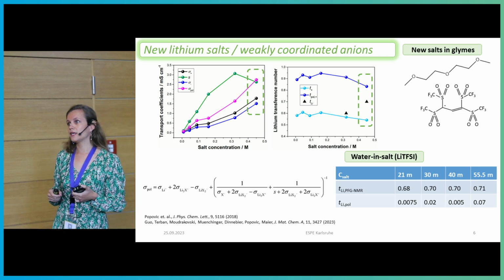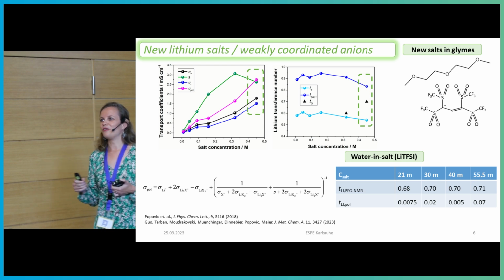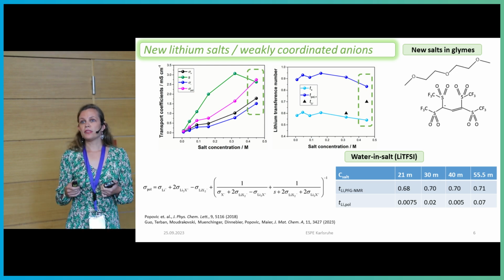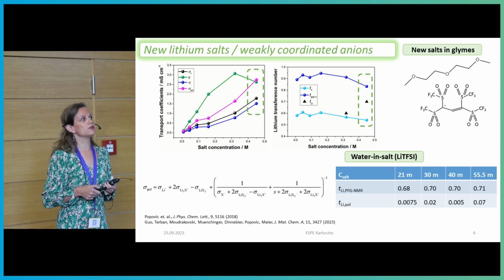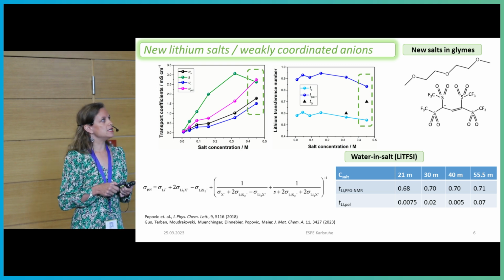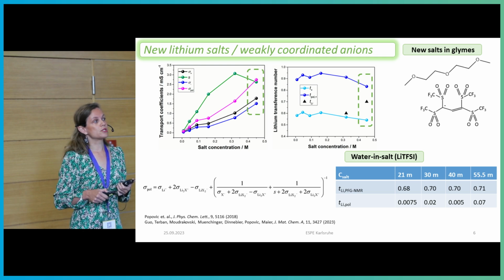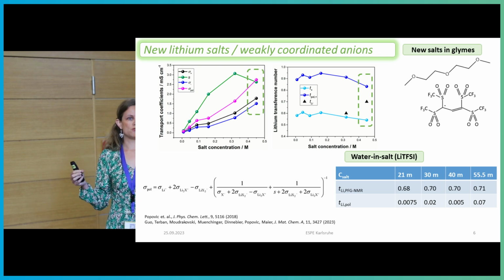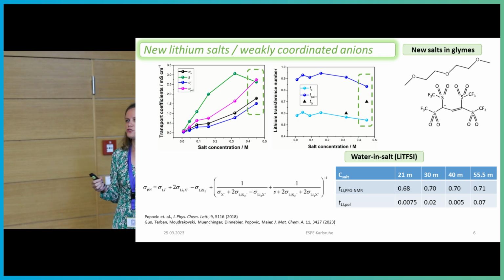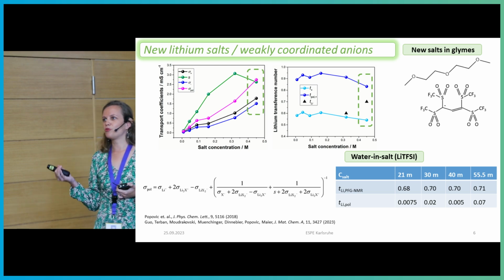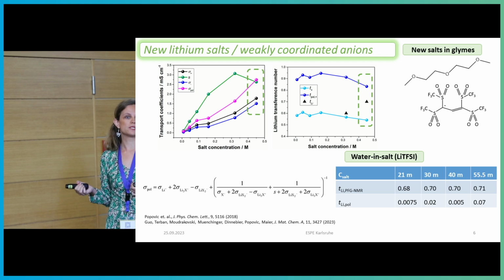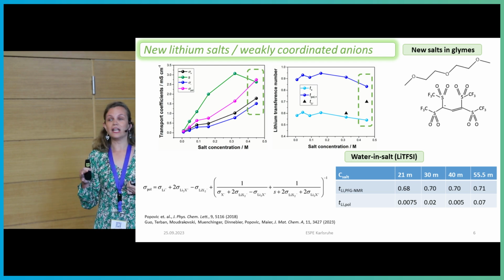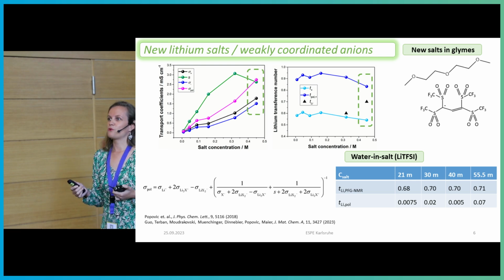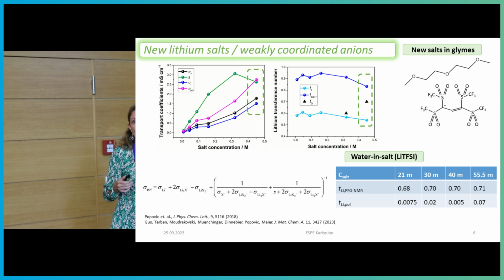So how can we explain that? And I think Monica already gave a little bit of insight into how that can happen. So if we think about a material that contains ion pairs and ion triples, for example, then we can see that from this sigma polarization, which is the conductivity in the polarized state, there is a possibility to have a situation where lithium is transported predominantly by negatively charged species. So it's a very similar type of behavior to what Monica already showed for ionic liquids. So in a way, we are barely moving lithium, in this case, in the right direction. So although we have very high ionic conductivity, the ionic conductivity is predominantly anion-based.